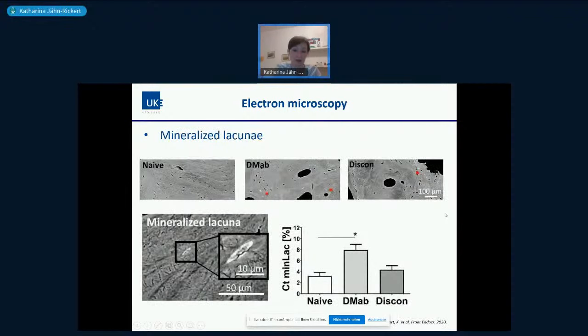Electron microscopy can also be used to look at mineralized lacunae. So what's that? When you think about a lacuna and an osteocyte sitting inside, there is a certain point that can happen in humans, at least we know, upon or after the death of an osteocyte, some of these lacunae can fully mineralize. You can actually see that the best probably here. So there's no cell inside anymore, and it's filled with mineral. And we also looked at this with the denosumab specimens and found that here in the cortex there was quite a high number of these mineralized lacunae.